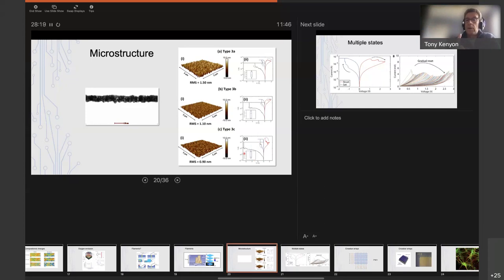And one of the things that's very important about it is what is the voltage that we need to apply in order to electroform. We want that voltage not to be too high, because ideally, if we were to make devices based on this phenomenon, we would want them to integrate with CMOS microelectronics. So we would want voltages of the order of a volt to maybe 3 volts, nothing higher than that. Well, for this very smooth surface, you can see the electroforming on the far left of this graph. We start off with very high resistance, so we're down in the nanoamp range at about a volt. And then suddenly this abrupt electroforming where we create the filament happens at over 6 volts. Here, where we have the roughest interface, that's reduced to about 3 volts.